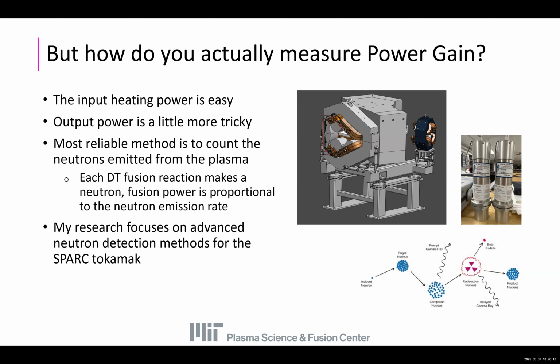And so, okay, if our goal is to make Q greater than 1, how do we actually know if we've achieved that goal? We need to somehow measure the energy or the power gain of the reactor. And so the denominator of that expression, the input power, that's pretty easy to measure. You could just call up the electrical company and say, hey, how much power did I use to heat up my plasma? And they'll say, oh, you used a megawatt or whatever. The output power is a little more tricky. And so the most reliable method that we have to actually measure how much fusion is going on, the power liberated from fusion, is to count neutrons. Since each deuterium-tritium fusion reaction makes 1 neutron, the fusion power will be proportional to the neutron emission rate. And so if you can count your neutrons, you can infer what the fusion power was.